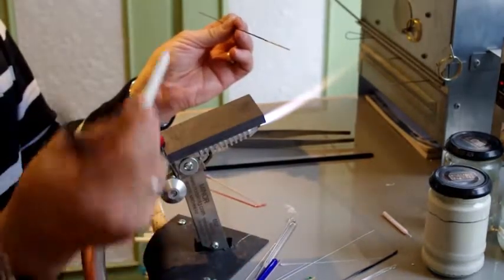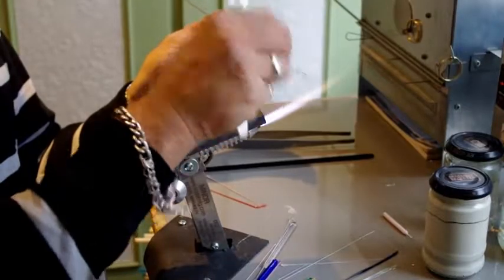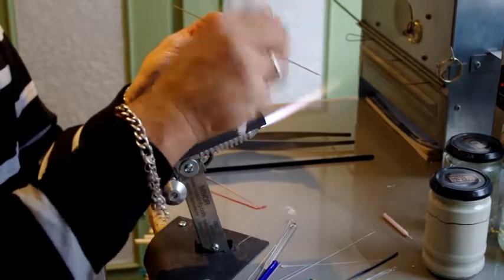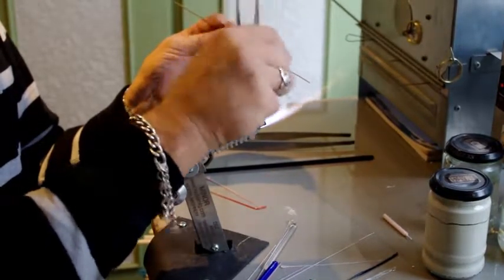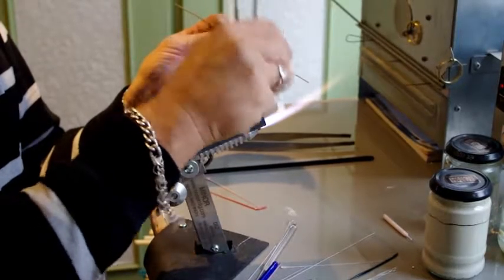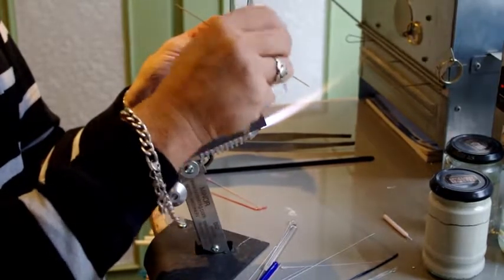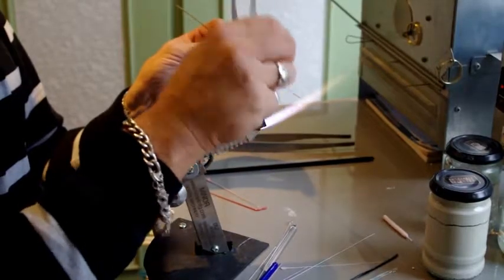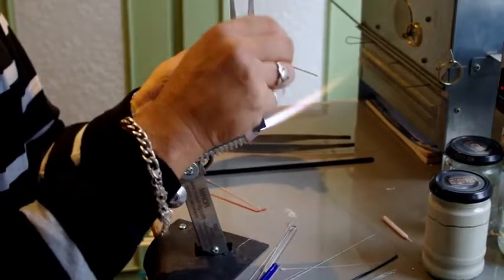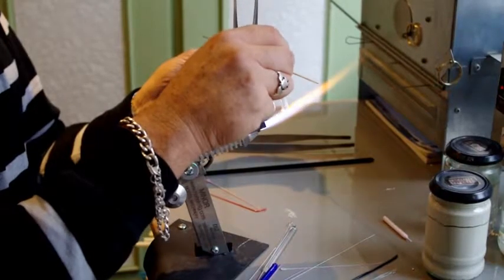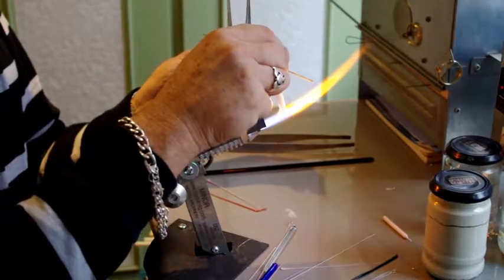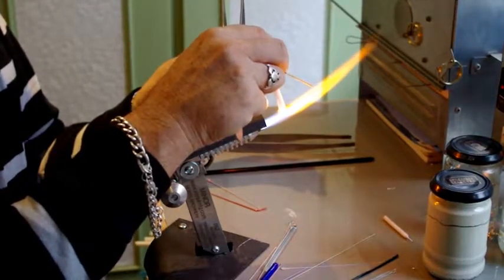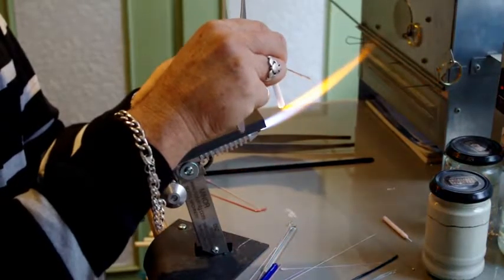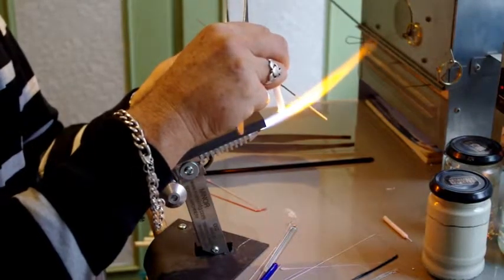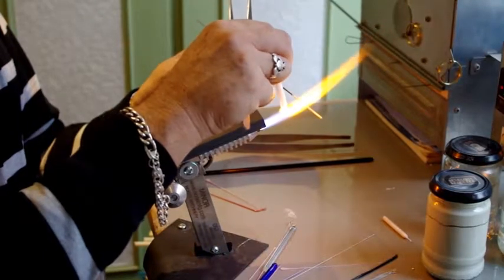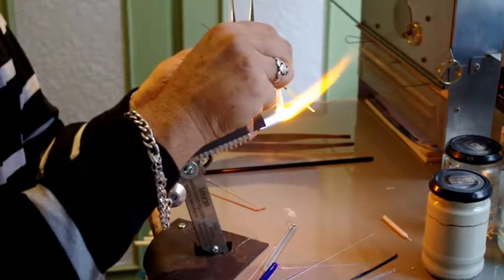then with a small rod of white we must preheat the white to bring it up to a temperature. If we just put it into the flame and hold it there, it will split, explode, break, pop, and you'll get hot molten glass all over your table and probably even in your lap, and it hurts. As you can see, we now have a steady flame.